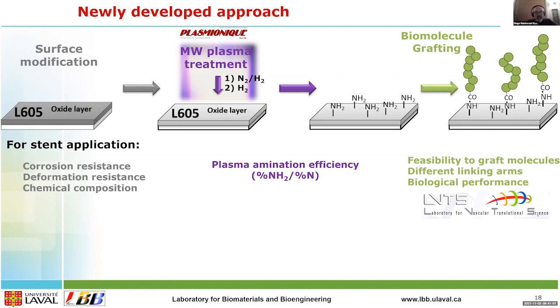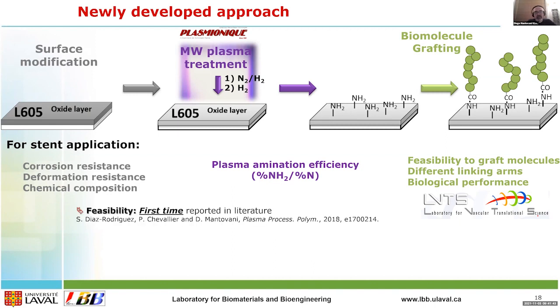So basically, for stent applications, attaching directly on metals limits the effect of the deformation and the corrosion, and eventually maximizes the chemical composition of the interface between the biologically active coatings and the metals. Plasma amination allows us to determine the number of nitrogen groups and optimize those that are mainly amine groups. And finally, the feasibility of grafting the molecule was assessed in vitro by our colleagues.